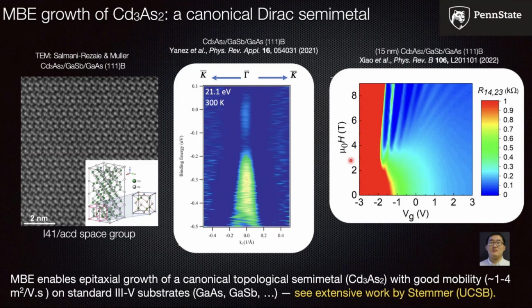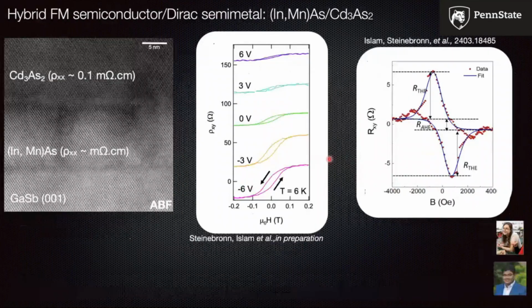And what I got interested in is, can you grow cadmium arsenide, this Dirac semi-metal, on a ferromagnet? Now, one would want to have a ferromagnet that doesn't short the current, right? So when you're studying quantum transport like this, you don't want your current to be flowing in the ferromagnet. So we tried growing on insulating ferromagnets, but just couldn't get it to work. And then I went back to my old background in manganese-doped III-V semiconductors, and said, what if we take a III-V semiconductor, put very little manganese in it so as to make a ferromagnet that's highly resistive, then can you do interesting things? And we can indeed grow very nice heterostructures.